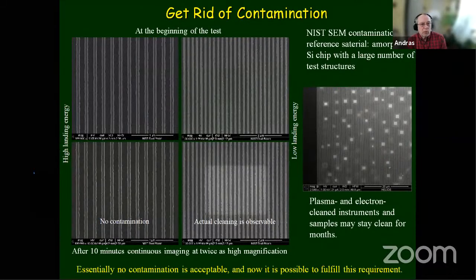Okay, very good. So contamination ruins the resolution and the sample. I don't want to go too much into this, it just shows that it could be horrendously bad. And this is a case when it is good, so you will not have contamination anymore. In the case of silicon, due to the vacuum system working in the 10⁻⁶, 10⁻⁷ range, you will have water on the surface, which will oxidize under electron beam irradiation. That's where the brightening happens, because you make the native silicon oxide thicker.